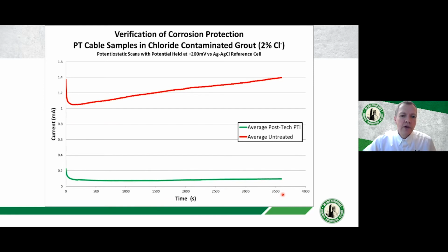And during that time frame, you measure the current, and you'll notice for the untreated samples, the current is much higher, and after stabilizing, it actually increases with time. If you look at the treated samples with the same voltage applied to them, the current is much lower, and maybe it slightly increases with time, but it's definitely much lower and much more stable, which implies you have a great increase in corrosion resistance.